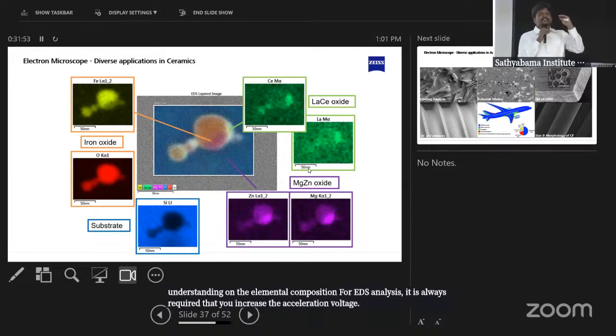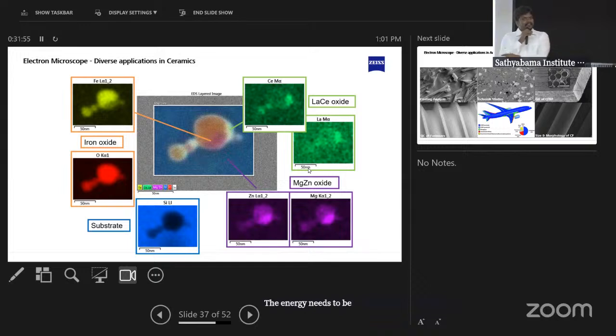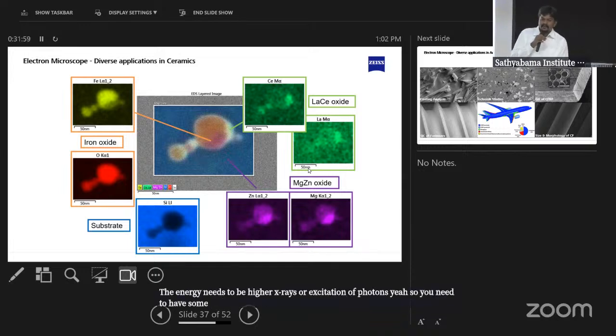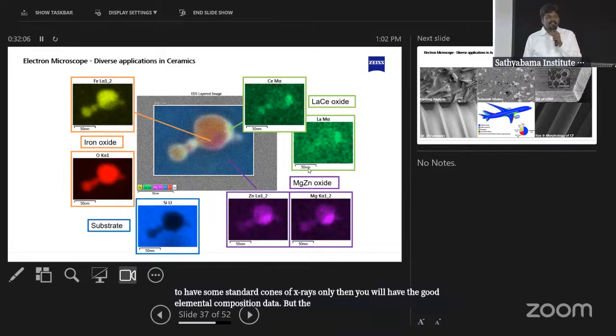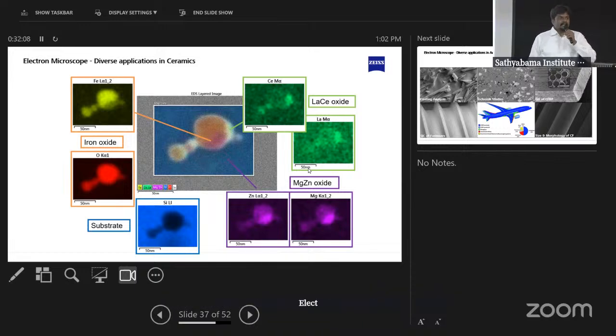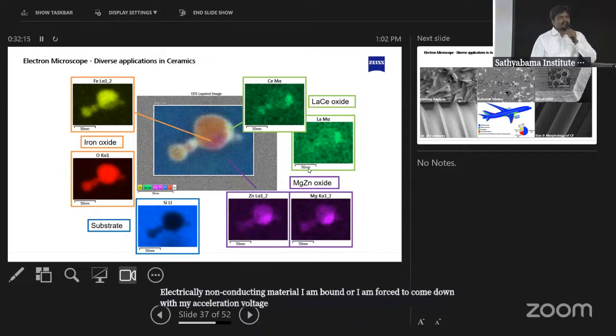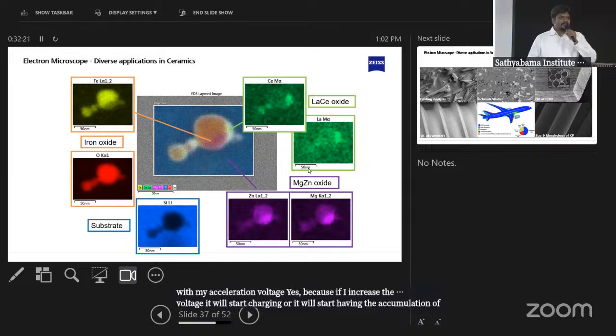Yeah, the energy needs to be higher because X-rays are excitation of photons. So you need to have some standard counts of X-rays, only then will you have good elemental composition data. But the challenge is the moment you talk about ceramics or electrically non-conducting material, I am forced to come down with my acceleration voltage. Because if I increase the acceleration voltage, it will start charging, or have an accumulation of energy, and I will not be able to have a clear understanding of the surface morphology.